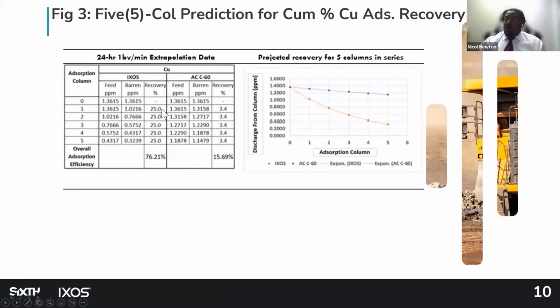The same thing was the result we had for copper when we did the extrapolation. We're thinking of recovering 76% of the copper compared to 15% using activated carbon. Now, with that in mind, we realized that if we recover the gold, we can also recover the copper, and depending on how our strip performs, we would be cleaning the beads and making it available to recover more gold and more copper as well.